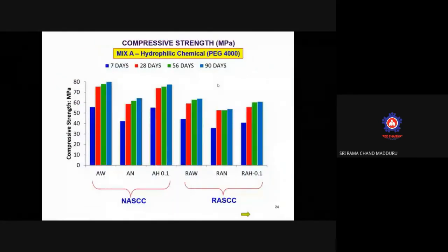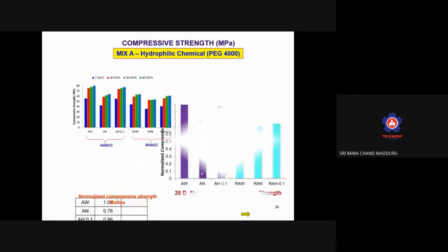So just understand here, this is the last slide of my presentation. If you understand the compressive strength, typically I'm showing for polyethylene glycol 4000, which is a hydrophilic chemical, having affinity to water. So here I'm comparing natural aggregate self-compacting concrete with the recycled aggregate self-compacting concrete. The amount of cement and water is the same, but there is a change in the aggregate content. So just see here,